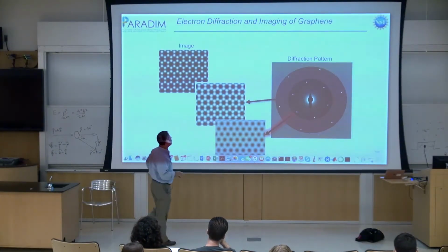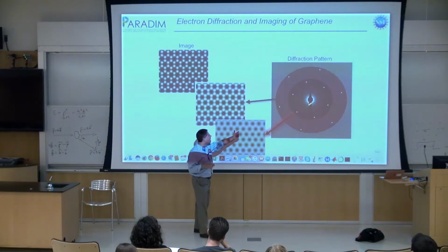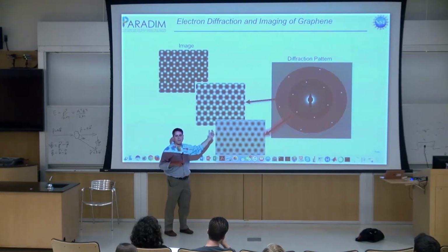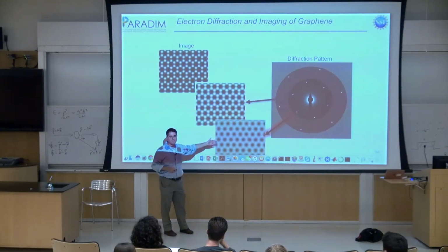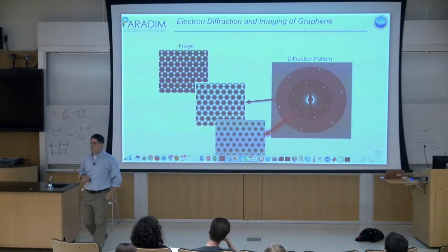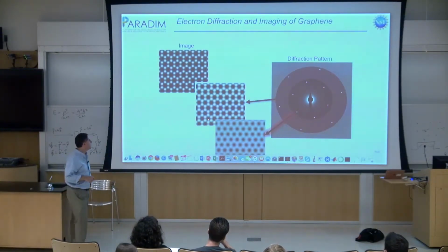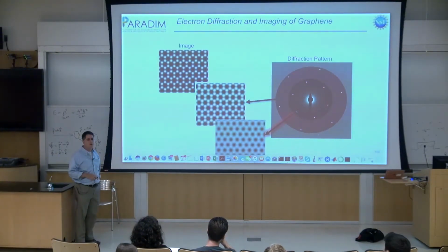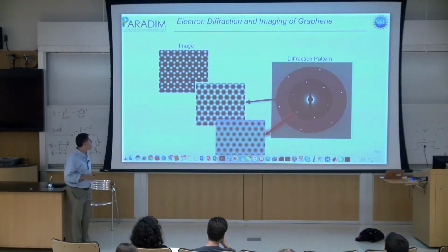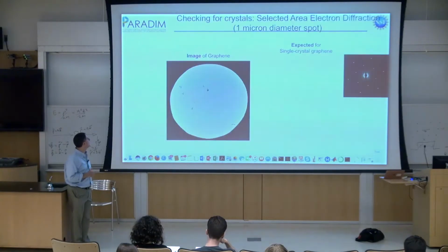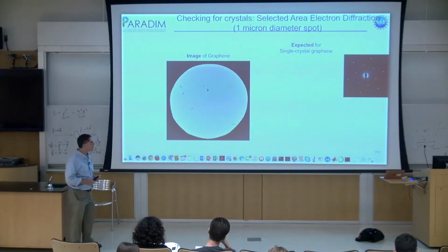The lesson I want you to visually clue in on in your head is that when you see spots in a diffraction pattern or an FFT, they just come from a series of sine waves that make up the image. And if I want to have a nice looking image, I need more than one set of sine waves. So when you're setting up your optics, you want to make sure that you can get enough information into the lens that this kind of diffractogram will pop up. Okay, I covered this one.